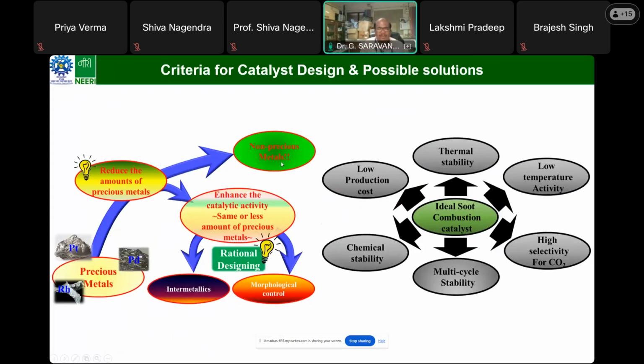But that eventually requires a lot of R&D. So currently, what we need to do is minimize the amount of these PGMs, so that we can enhance the activity by using the same or less amount of these PGMs, so that we can minimize the consumption. There are certain approaches. One is to develop alloy or intermetallic catalyst formations and morphological controls. So what is required for a typical diesel soot oxidation catalyst? It should be stable up to 800 degrees.